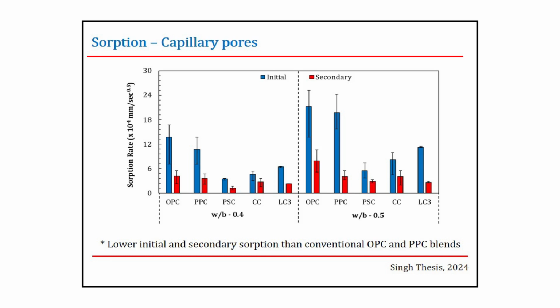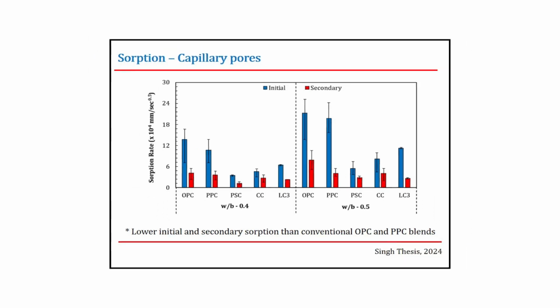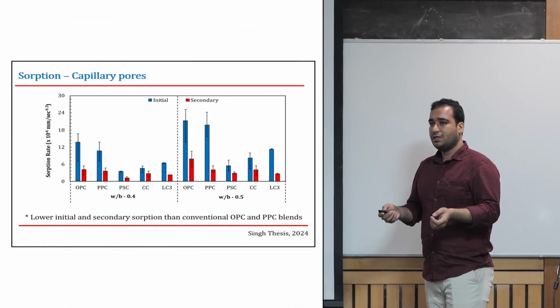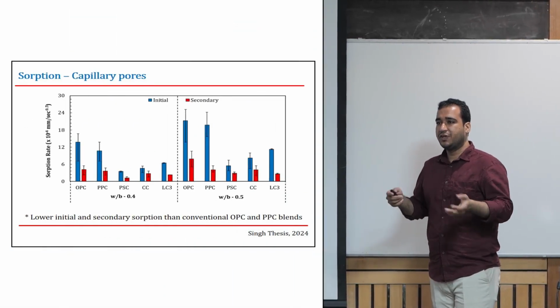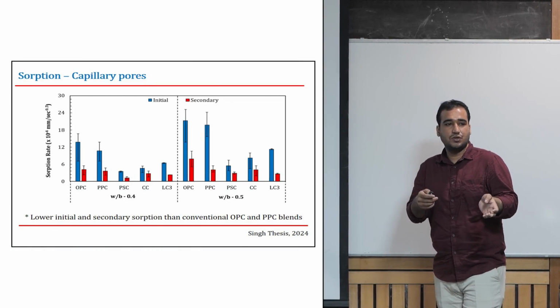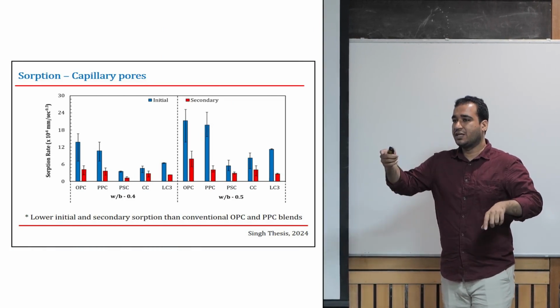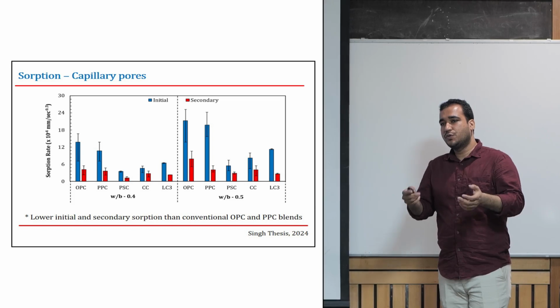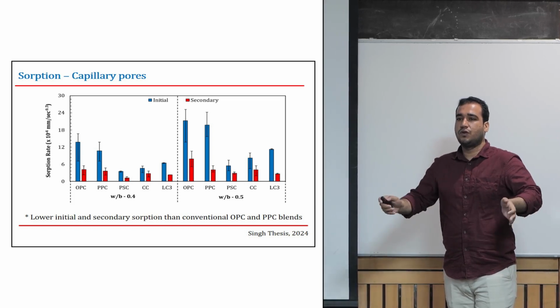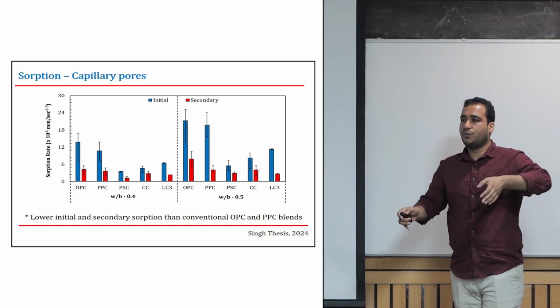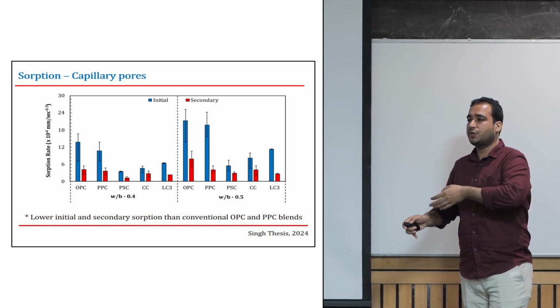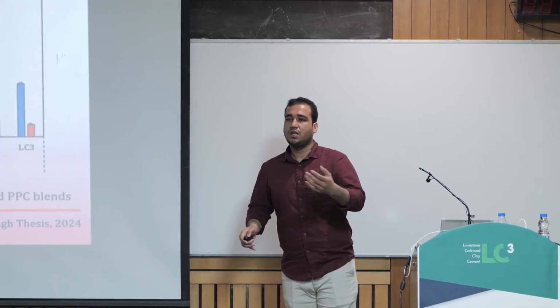and how it influences other properties. One of the quick methods is absorption. Water absorption rate and water absorption are two different things. Rate gives you an idea about the rate of ingress. Water absorption gives you the total volume that gets absorbed. It gives an idea about porosity, and this one gives the rate of the ingress of the moisture or, say,